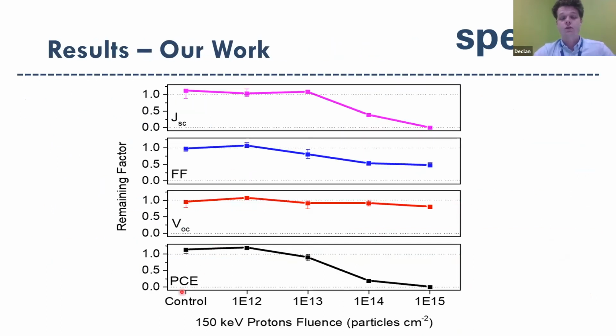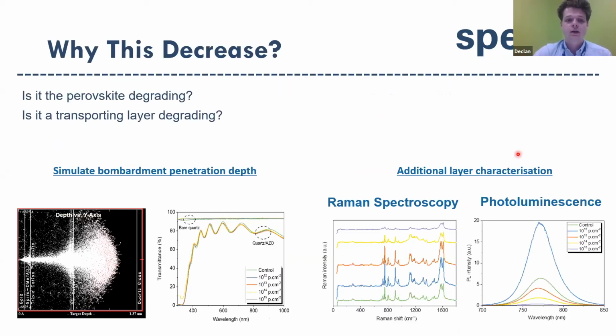In terms of the actual results, we found that at 10^13 the devices are very stable. Then at 10^14 and 10^15, the device performance decreases along with the JSC. So our mindset was, why is this the case? We looked at whether it was the perovskite or any of the transporting layers. We simulated the device structure and the bombardment, and found that most of the protons stop in the AZO. So we looked at the UV-vis for the AZO and quartz and found no change in relation to proton fluence. So there are no color centers forming, which is obviously good news.